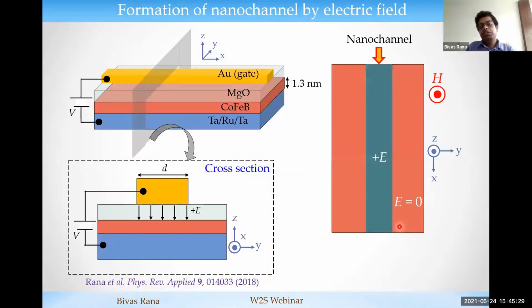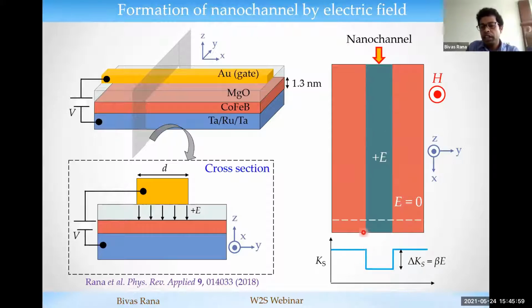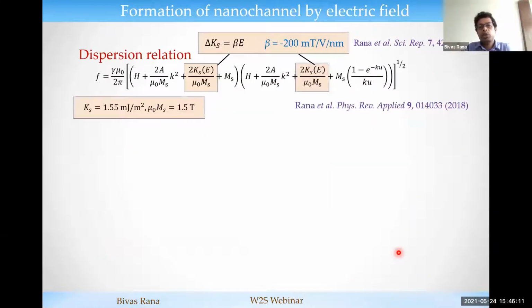And our proposal is different. So what do you have to do? Basically, you make a top gate electrode made of gold, with a dimension smaller than the dimension of the waveguide, then apply a DC gate voltage. You can tune the perpendicular anisotropy right underneath this gate electrode, and that creates some kind of virtual channel in the system, where if you take a line scan across this dotted line, you can create a kind of potential well where you can confine the spin wave. This is how we can confine the spin wave by a VCMA-induced virtual nanochannel.